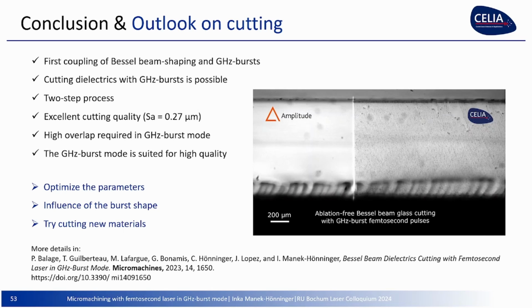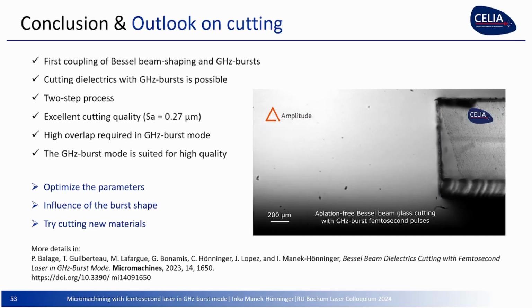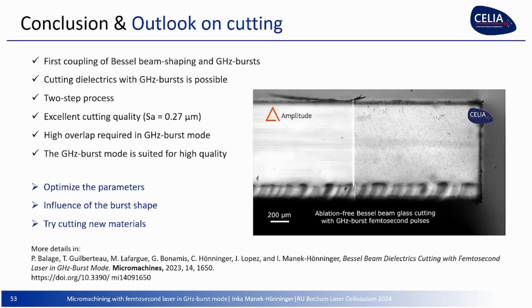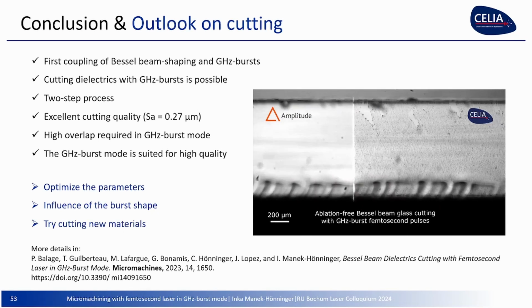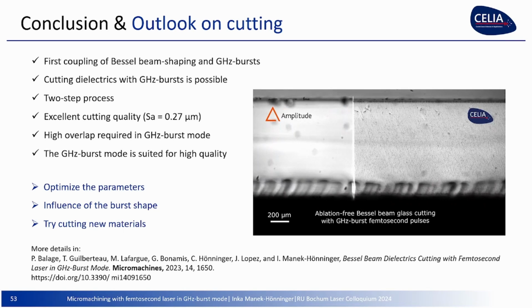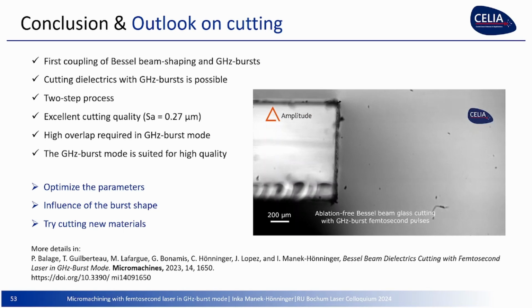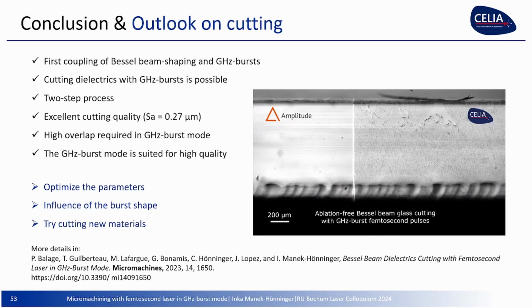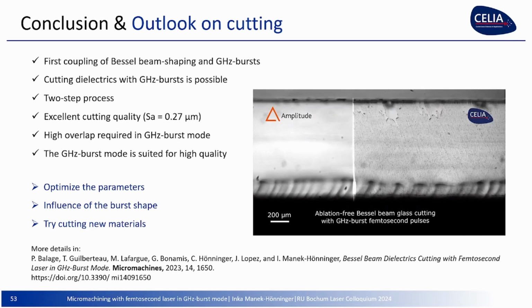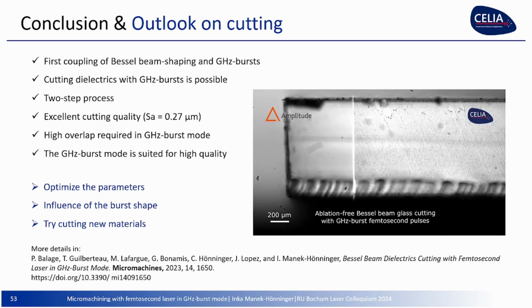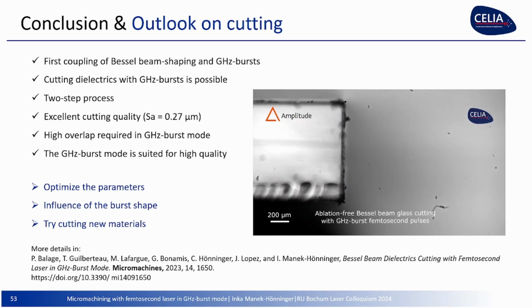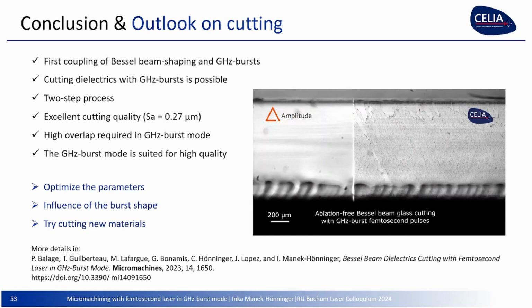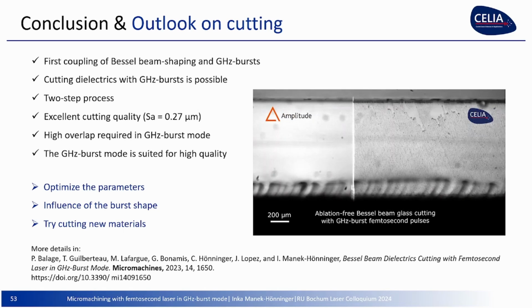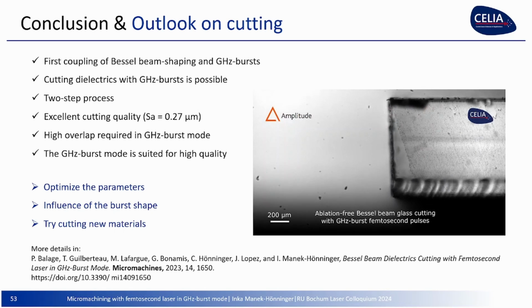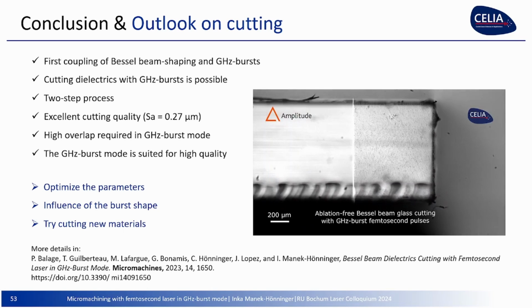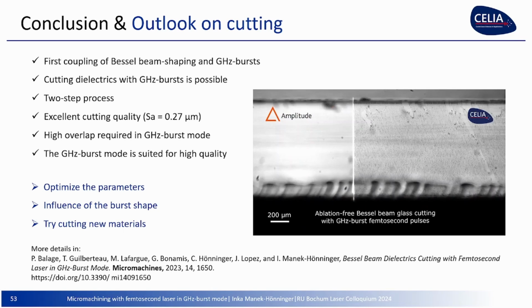So we were the first to couple this gigahertz burst shape with a Bessel beam, and it works, and it gives good quality. It's slower, we saw. What you see here on the film, this is a soda lime sample, which is moved into the Bessel beam, and here it's pristine, and here we have this pre-cut zone viewed by camera. You can see that. What is still to do? Of course, optimizing parameters, looking at the influence of the burst shape, and trying other materials. Of course, other materials are quite interesting.